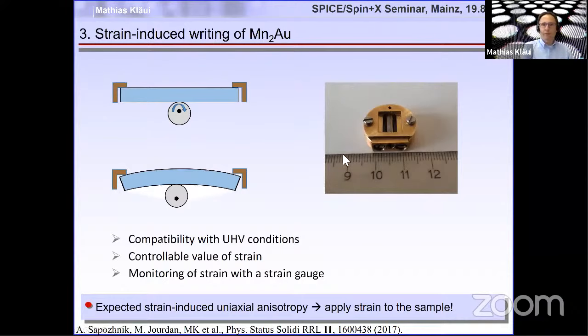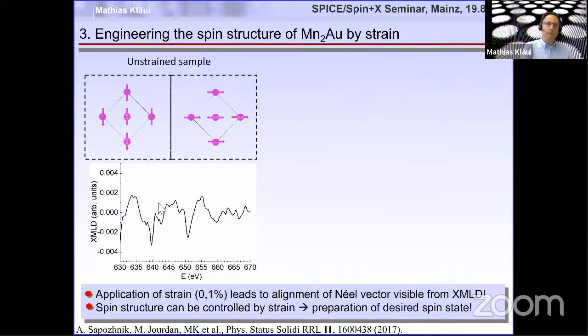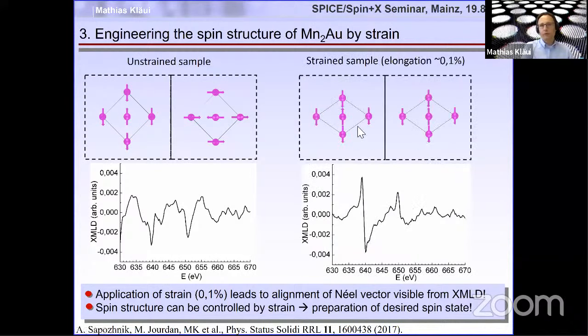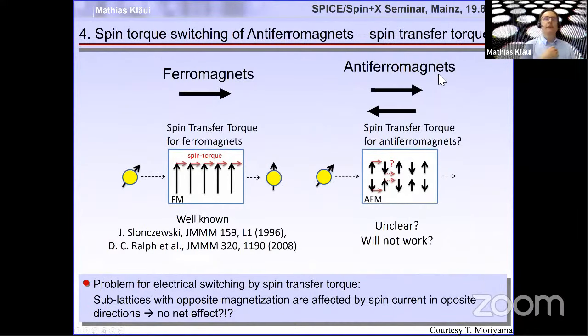And before that, we actually see that for an unstrained sample with a multi-domain state, we see no net XMLD signal. And when we strain it and we generate a uniaxial anisotropy that aligns all the spins in the sublattices in one direction, we get this XMLD spectrum showing that these are aligned for just 0.1% elongation. Okay. Now, this is, again, not very practical for applications. So in application, you would like to have all electrical writing. So how can we do all electrical writing?